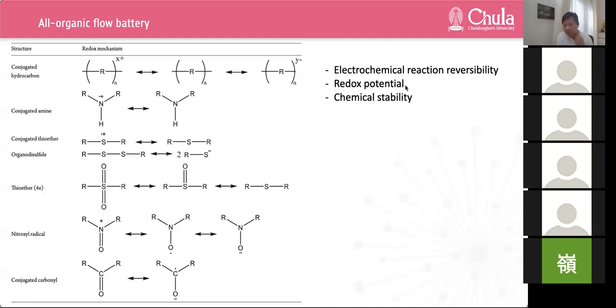And the next factor is redox potential. And this factor determines the side on which the organic can be used. Generally, P-type organics such as nitroxyl radical have a higher redox potential than N-type organics, for example, conjugated carbonyl. In addition, in quinone-based organics, electron withdrawing and electron donating groups can effectively tune the redox potential. Solubility: small organic molecules tend to dissolve in either aqueous or non-aqueous electrolytes. In addition, a proper substituent or a change of structural symmetry can effectively increase the solubility of organic materials.